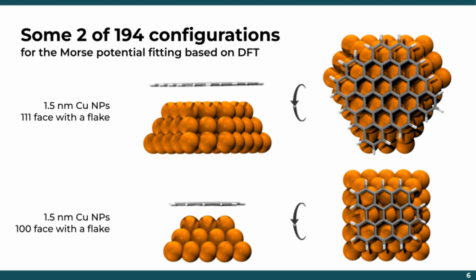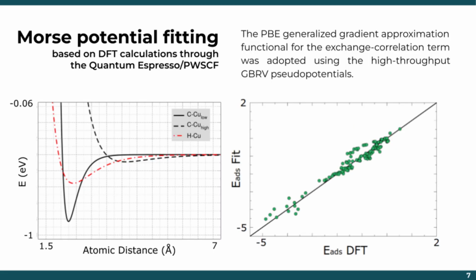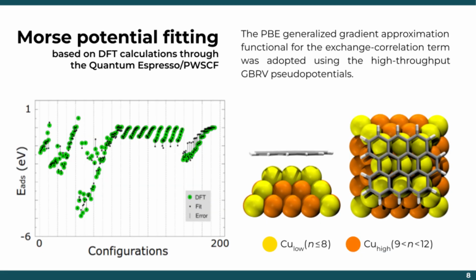simulations. It was applied in 194 configurations, consisting of a single flake in different orientations and curvatures, on a portion of each phase of the copper nanoparticles. Then, single-point energy calculations were done, obtaining a good agreement between the quantum and classical simulations where the potentials were applied. In Quantum Espresso, the PBE generalized gradient approximation functional for the exchange-correlation terms was adopted, using the high-throughput GBRV pseudopotentials. The best fitting was achieved when two different types of copper atoms were considered.